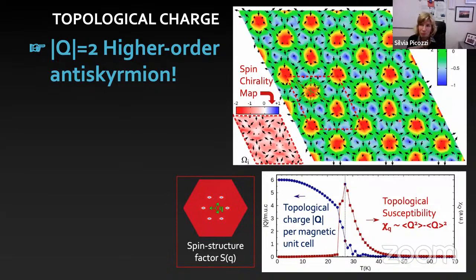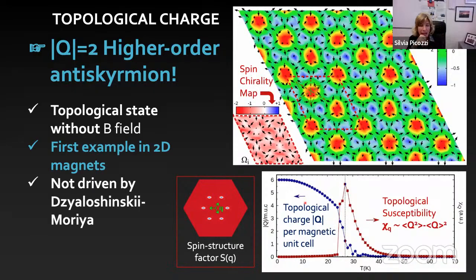But in our case, we do, right? This is what we get. And also we don't have, let's say, a bare skyrmion. We have an anti-skyrmion with topological charge Q equal 2. And so via Monte Carlo simulation, we could estimate again the Curie temperature here by calculating this order parameter, the topological charge per magnetic unit cell. And so here we have a topological state without magnetic field. It's a lattice. It's not a single isolated skyrmion.